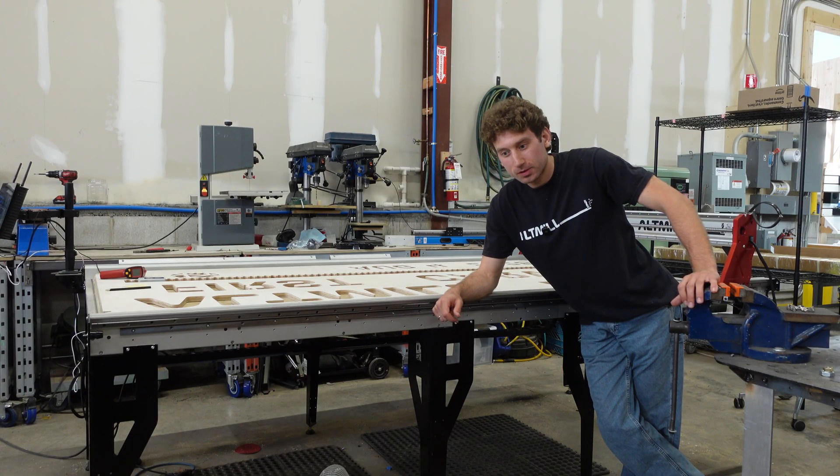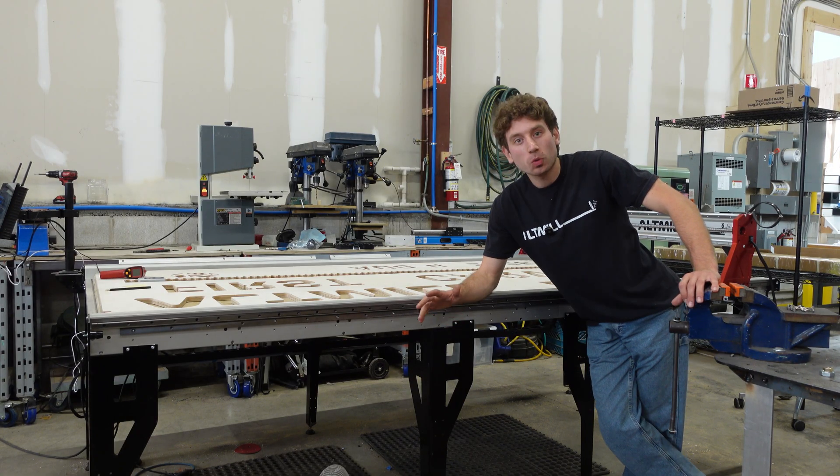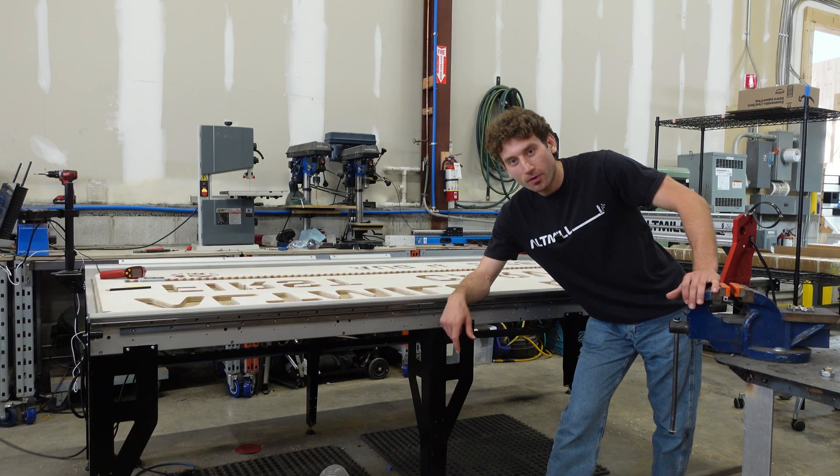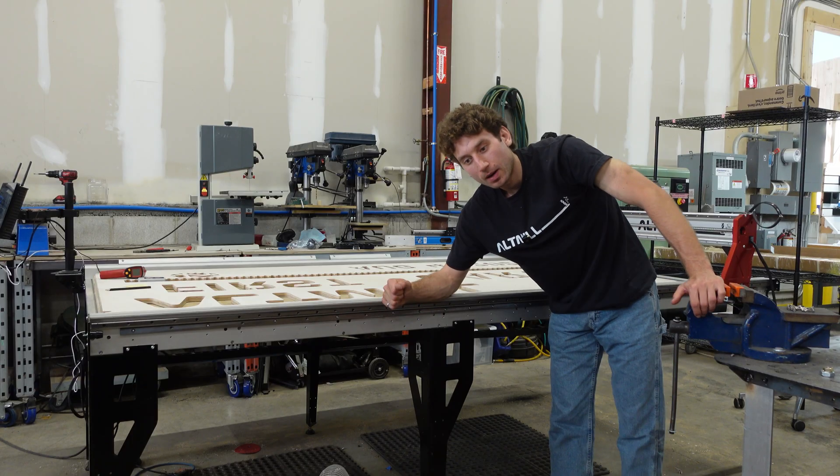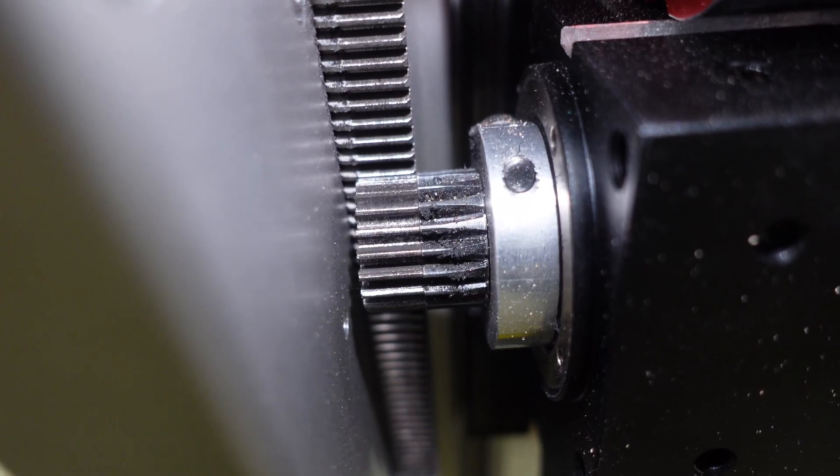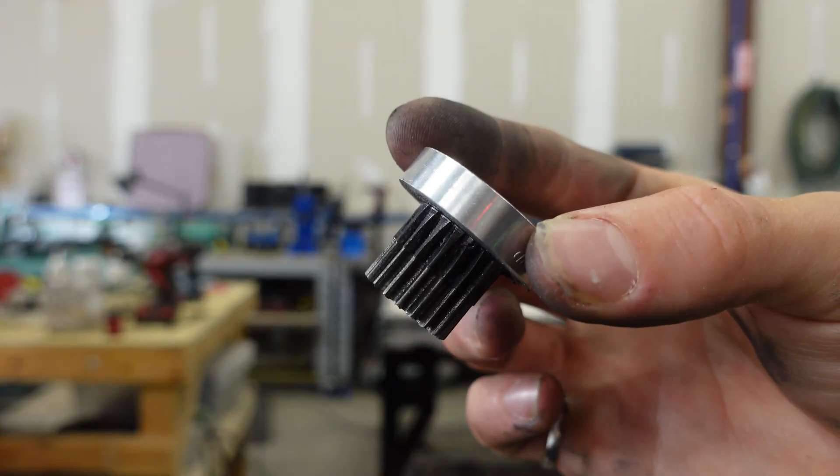The machine moved in the range of 17 kilometers, 26 hours of moving back and forth. The pinions are worn down. This is kind of like the worst form of setup. We ran this no lubrication. I'm going to see how much it wore the rack out compared to how much it wore the pinion out. You can see that lip there.